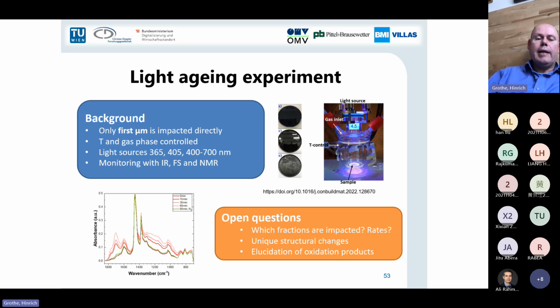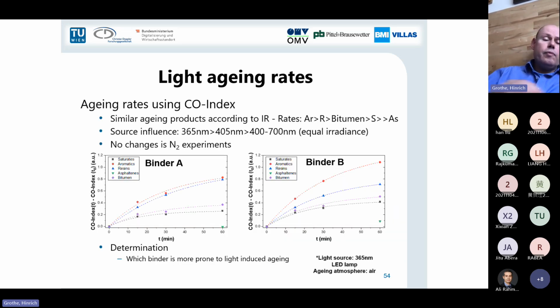So we were running some light aging experiments, and we had light sources. We could apply different wavelengths. We could monitor with infrared, fluorescence and NMR spectroscopy our light aged samples. And the questions we wanted to answer: which fractions are impacted? We were looking for rates, for structural changes, and for oxidation products. And here, this aging was done for 2 different binders and for all 4 fractions. And you can really see that saturates are only little altered, while it's mainly aromatics and resins which show a very strong change in this aging.